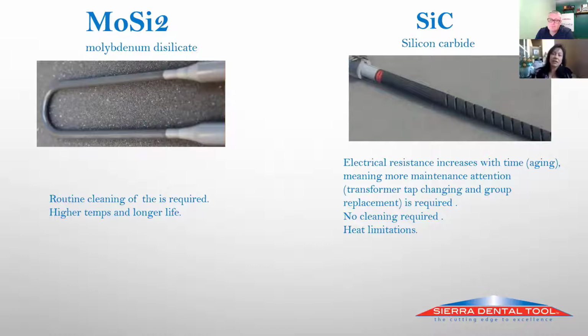They don't necessarily get contaminated. That's the good thing, that's why people like the silicon carbide, they don't get contaminated. But they do have a shorter life, and you can't achieve as high of a temp without shortening the life of them dramatically. Now with the MoSi2, those do get contaminated, but it's easily taken care of by a purge cycle that you could do over the weekend. Press play, go home, come back, and they're purged.